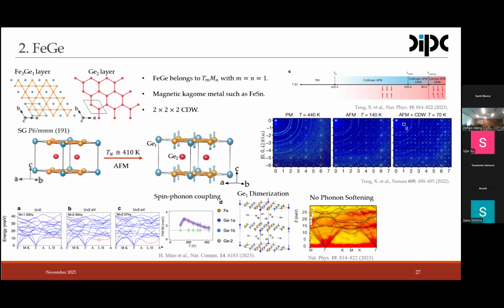Is that correct? Yeah. So there is actually a controversy about the origin of this charge order transition. It's actually a complex problem because, first, the DFT calculations do not show any soft mode in the spectrum. Then the group of Hu-Miao measured the temperature dependence of the out-of-plane vibration, which I think is the trigonal germanium atom, and sees a strong broadening which renormalizes below the phase transition. In order to get this broadening of the peak, they introduce correlations in the DFT calculations, and they actually see how the phonon gets soft.